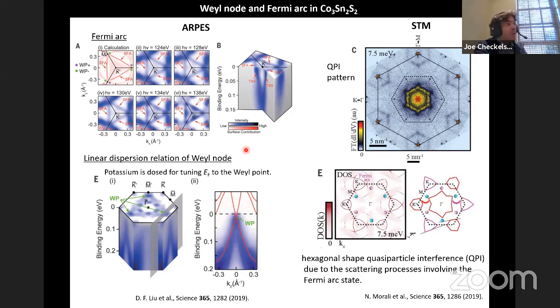There's notions that, for example, if you apply a magnetic field to one of these Dirac semimetal systems, you can split it into Weyl cones. And at that point, you could measure things like the chiral anomaly that are associated with the number of Weyl cones. You could also measure what people refer to as a quantum Hall effect, which basically measures the spatial extent in k-space, I should say, of the Dirac cone separation. So yeah, that's right. For all of these additional cones, you should basically affect some kind of multiplicative aspect. Of course, if there are different energies, then that complicates the situation.